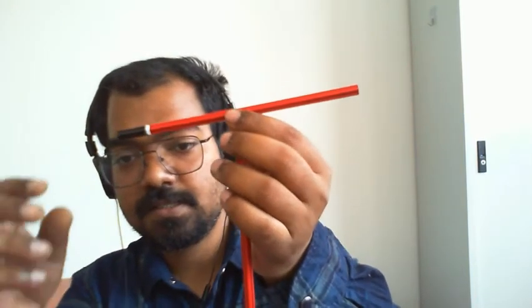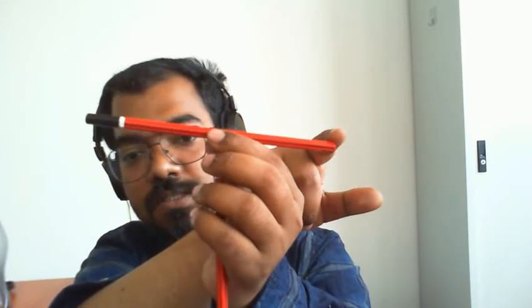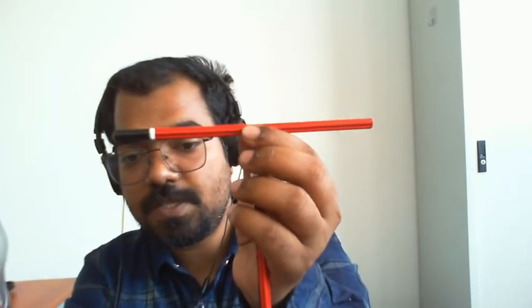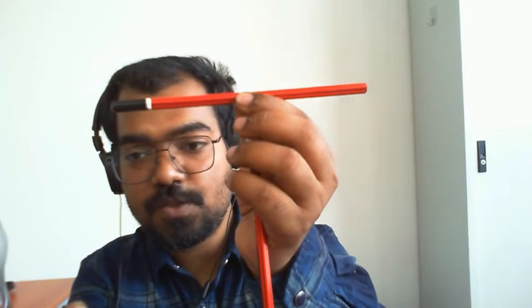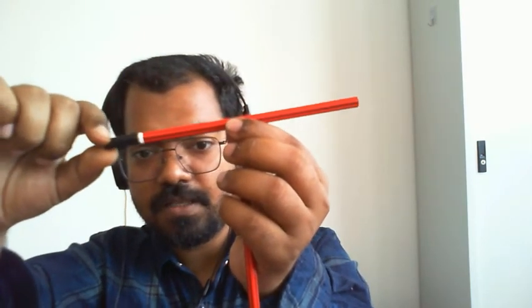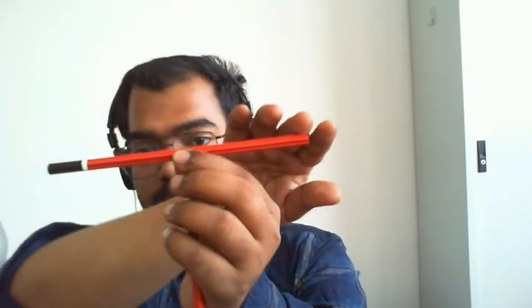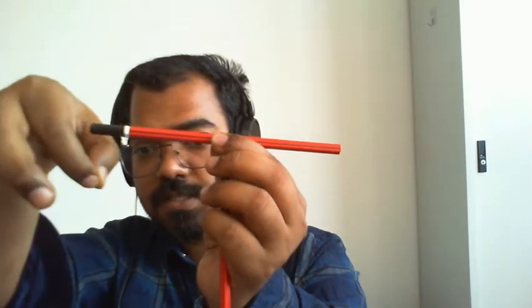So you hang the specimen, and the rod stands on a fulcrum like this, and you hang the specimen from one end and you apply the weight on the other end, and that much amount of force is applied on the specimen. The lower part of the specimen is fixed, of course, and the upper part is attached to this rod. The other end is connected to where you have the force, and that force is trying to pull this rod down, and because of that you have force on this end, and that pulls the specimen up. Then you measure the displacement on the specimen, and from the displacement you calculate the strain, and you see that under the constant application of load, the strain increases with time. So you are not changing force, but still the displacement is changing.